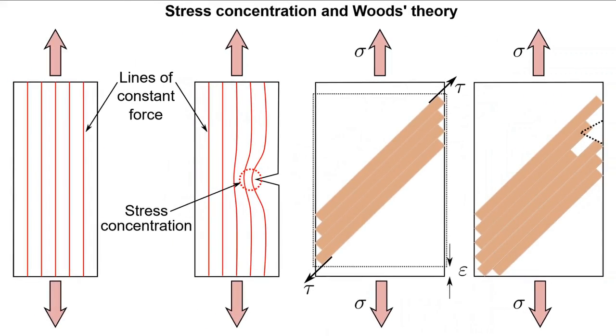With a stress concentration, this means that the local stress around the flaw can increase beyond the yield stress. This is Wood's theory, which explains why fatigue cracks initiate and explains why fatigue cracks appear near the surface of materials. We'll cover other microstructural features that can also create these types of stress concentrations in a future lecture. But for now, let's examine how these cracks can propagate.